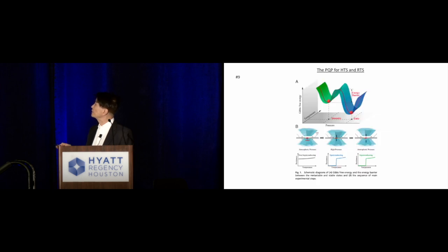So the idea is this: when you apply pressure, at the beginning it's not even superconducting, as you can see here in the diamond cell. You put the sample here, you apply pressure, squeeze it, and then finally it goes through a transition and gets into a superconducting state. Then you remove the pressure and try to retain the superconducting state. That's what we call the pressure quench for high-temperature and room-temperature superconductivity. And that's what we are now striving for, working very hard on.